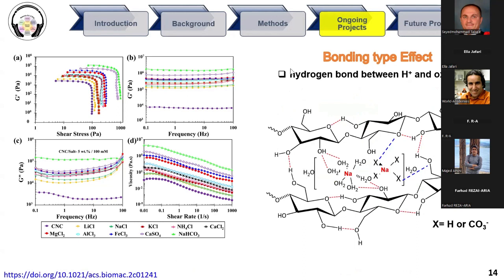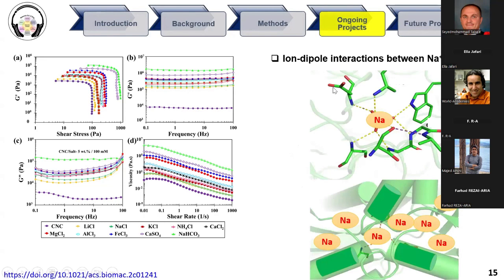For example, for sodium bicarbonate, we have Na aside from HCO3 negative, and this Na can form an ion-dipole interaction between the Na particles and water or the OH groups of cellulose. So whenever we form this type of bonding, it acts as a bridge, and we are going to increase the network. This will increase the viscosity, so we can form this network between particles.